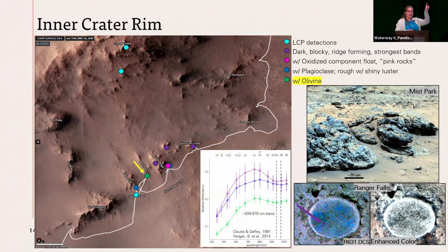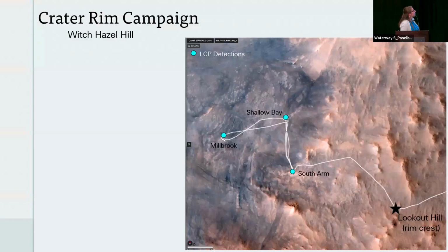We don't have these nice 900 nanometer pyroxene bands. We don't have a nice 1 micron olivine slope. Instead, we get these shifted bands that vary between 940 and 980, which is consistent with a mixture of olivine and low calcium pyroxene.